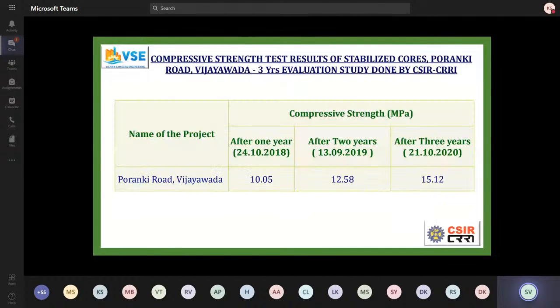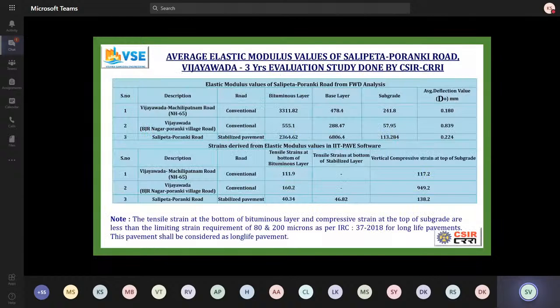This is the strength. Again, CRRI tested this road 2 weeks ago, and this is the strength they have achieved. It's actually gone up. Again, FWD was done on these roads. Very interesting, there was a national highway done by Dilip Buildcon, which is adjacent to our road. So we did a comparative study, just to see how our stabilized road fares versus a national highway, which has I think DBM of almost 80, 90 mm and 45 BC. And of course, since this is a national highway, the GSB and WMM thickness was close to around 400.